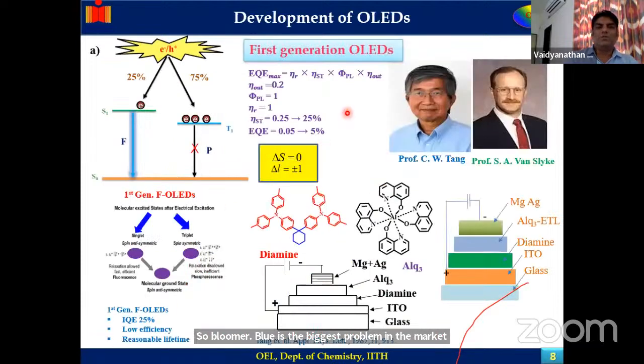Okay, as I have told you, the first generation OLED was discovered by Tang and Van Slyke at the Kodak company in 1987. They said that in the first generation OLED, the singlet, the spin antisymmetric state, gives only 25%, whereas the 75% goes as waste. They used Alq3 as an emitter and fabricated this device, getting an internal quantum efficiency of 25%, whereas the external quantum efficiency is 5%.